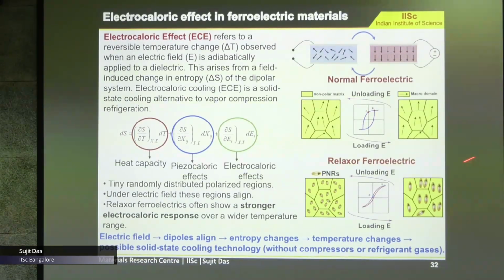Similarly, you can also have a relaxor ferroelectric. In the relaxor ferroelectric you have polar nanoregions, and if you apply the field, these polar nanoregions are basically aligned, and relaxor ferroelectrics often show a stronger electrocaloric response over a wide range of temperature. So here we apply the electric field, we align the dipoles, we change the entropy, and then the temperature changes, and that could be used for possible solid-state cooling technology without compressors or refrigerant gases.